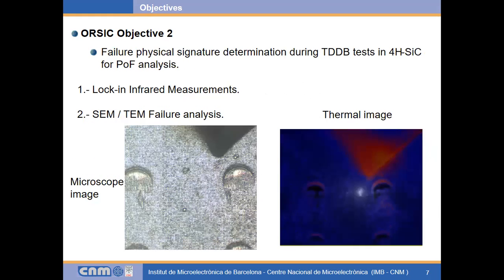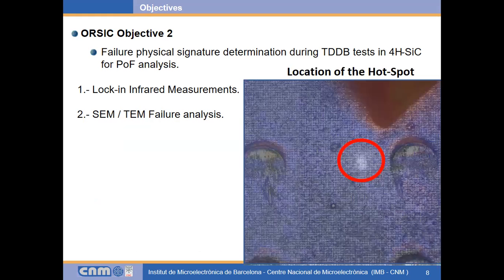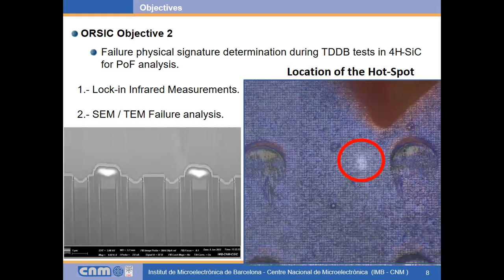Second objective relates to the physical signature of the TDDB test. We would like to perform lock-in infrared measurements complete with SEM failure analysis. At left we have a microscope image of one device which has failed after a TDDB test, and at right we have its corresponding thermal image. If we couple both images, it should be possible to locate the failure, and using the same analysis, we would like to inspect and find the failure, to analyze the weakness of the component.